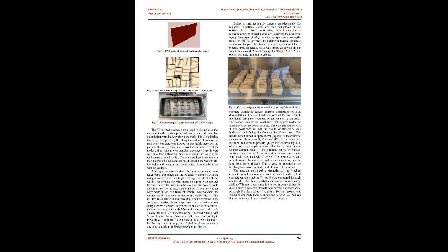Concrete samples with model cracks of varying widths between 1 mm and 2.5 mm were created by placing triangular polyvinyl alcohol, PVA, wedges in the concrete mold and pouring concrete around the wedges. Potato dextrose agar, PDA, growth medium and a 14-day culture of T. reesei fungus were inoculated into the cracks of 14-day-old concrete samples, which were then incubated for 14 days. The compressive strength of the concrete samples was measured after this 28-day period. These measures of strength were compared with the measures of strength for control groups, which were concrete samples lacking a crack, fungal inoculation, or both.